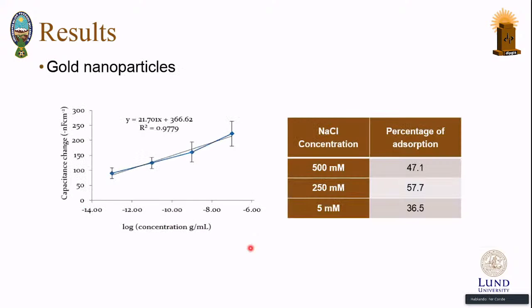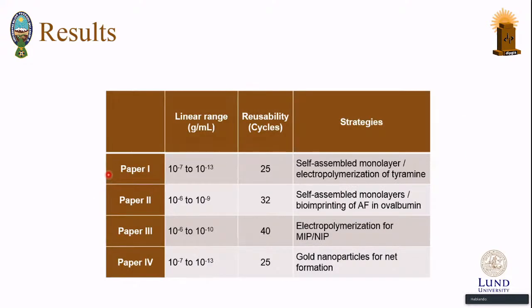When using gold nanoparticles, we have seen that the best option of sodium chloride concentration in order to reduce the repulsion between gold nanoparticles is the concentration of 250 millimolar, with a percentage of adsorption of antibody of 57.7%. As we can see in the linear range, we have 10 to the minus 7 to 10 to the minus 13, which is the same as when we are using electropolymerization of tyramine. In paper 1, we can see that the linear range is 10 to the minus 7 to 10 to the minus 13, having a reusability of 25 cycles when using electropolymerization of tyramine.